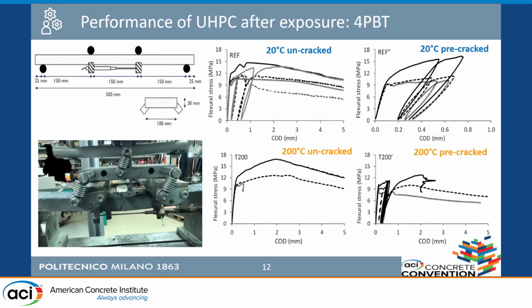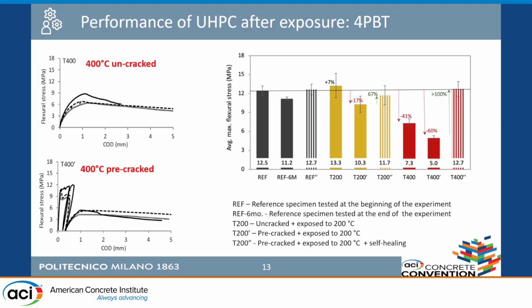You see that we have differences. We have important differences in the maximum strength that we can reach. So we have an influence of this, and this can be information to be taken into account when we perform the characterization at high temperature of concrete material.